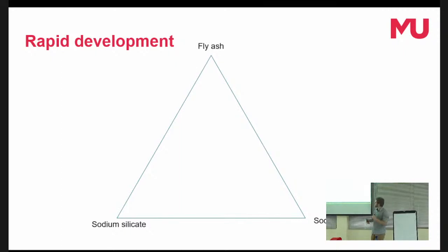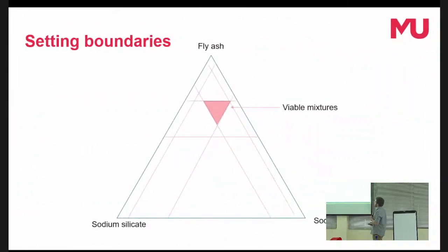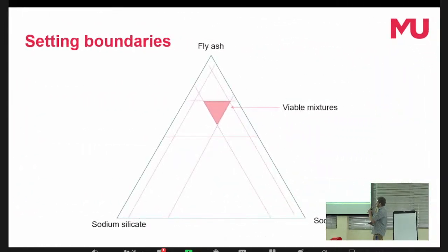So next slide, please. So we know that you need a certain amount of sodium silicate, but not too much. I found that adding more than 30% actually just makes the product swell in there by absorbing water and then cracks. So it's not more suitable for construction. But at the same time, you do still need a certain amount to give improved strength. There's a similar situation with sodium hydroxide and also with lime.